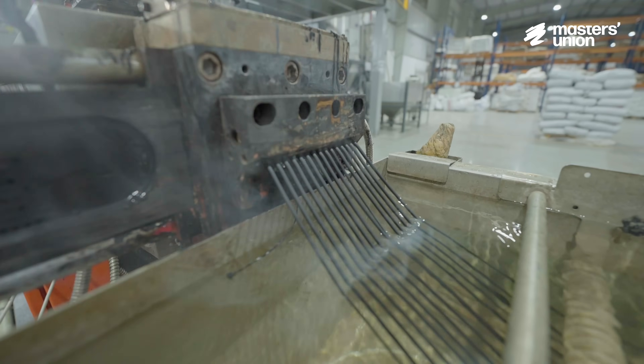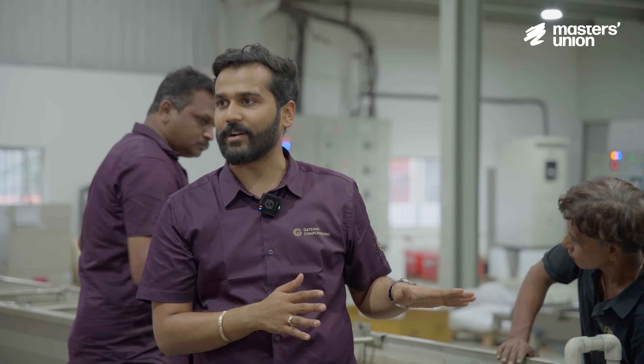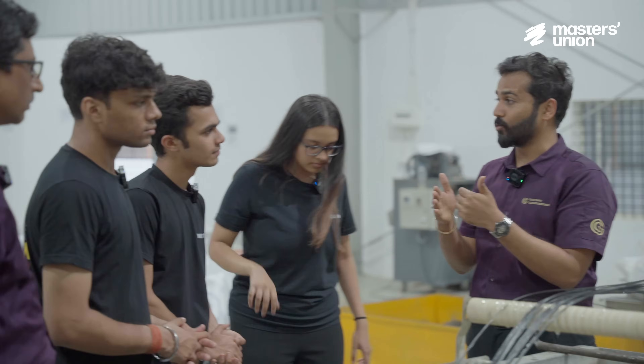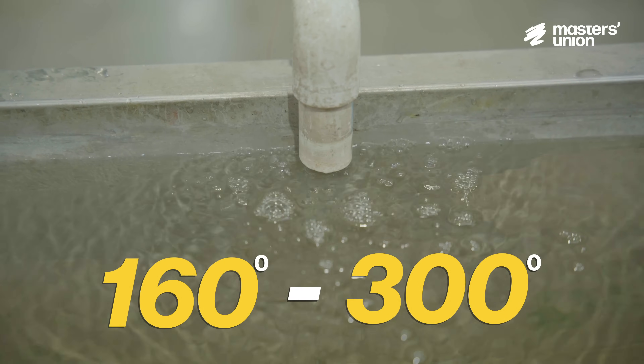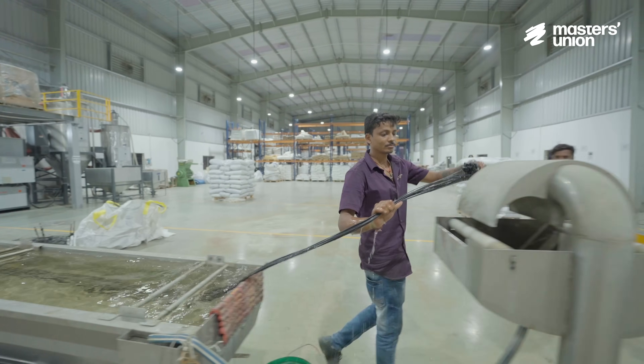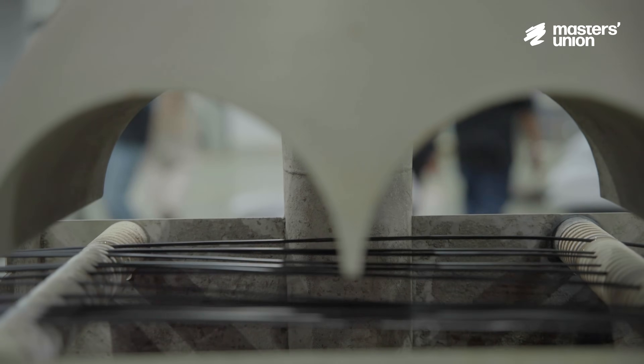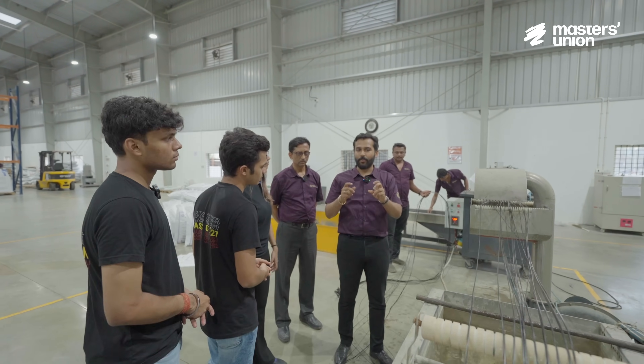Blending happens and these strands come out. The strands are put into water and we ensure a controlled temperature of the water to make sure the polymer is not affected. The plastic extrusion happens anywhere from 160 degrees to 280 to 300 degrees. When these strands come out, they're very hot and at times they carry water with them. So this is called an air knife — there's very high pressure of air which pushes the water down and ensures that the strand going into the cutter has no water residue on it.